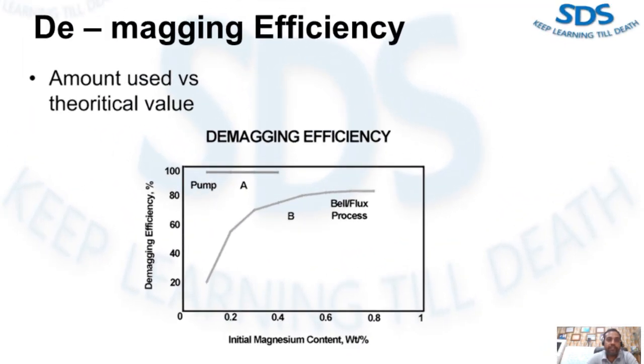Okay, now let's discuss demagging efficiency. The actual efficiency is very near 100% for the demagging process using the gas injection pump, versus an earlier technology that employed a static injection lance and a bell to collect fumes plus a wet scrubber. Efficiency is measured by the amount of chlorine utilized to remove a pound of magnesium compared to the theoretical value, which is 2.95 pounds of chlorine to remove 1 pound of magnesium.